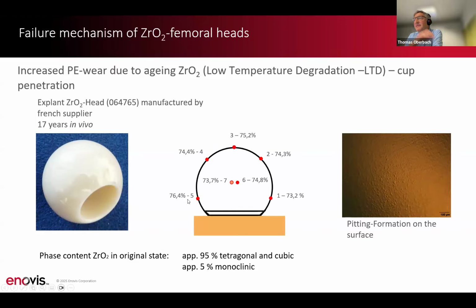And the phase transformation from tetragonal to monoclinic is combined with an increase in volume by about 7%. And if this occurs on the polished surface of the hip head, then this leads to a formation of pittings. That means an increase of the roughness. And if you have an articulation partner which is a softer material like polyethylene, then this leads to a higher polyethylene wear, to osteolysis, and to a necessary revision of the implant.